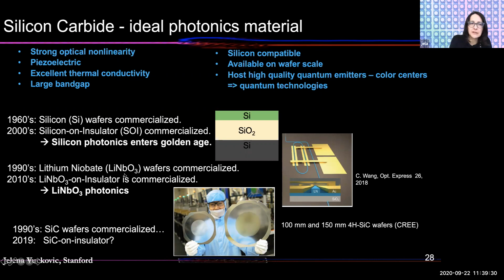And same thing happened with lithium niobate about 10 years ago when thin film lithium niobate became accessible. That was again about 2 decades after bulk lithium niobate wafers were commercialized. And in the past 10 years, we've seen a lot of exciting results on thin film lithium niobate platform. On the other hand, silicon carbide was also commercialized in the 1990s. That's bulk silicon carbide. You can get it in 6-inch wafers, for example, from companies like Cree, but there was no commercial silicon carbide on insulator as of last year. And we had to come up with the process to produce it with very high quality in order to do all of these experiments.